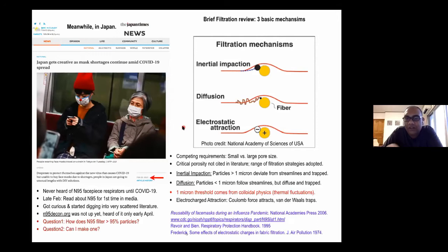This 1 micron threshold is basically, to my understanding, coming from colloidal physics. This document itself did not say anything about where this 1 micron threshold came from. But when we study colloidal physics, we say if you want a colloidal particle that is responding to thermal fluctuation, we say we should stick to about 1 micron or lower diameter. But that does not really explain why it should follow inertial impaction if it is greater than 1 micron.